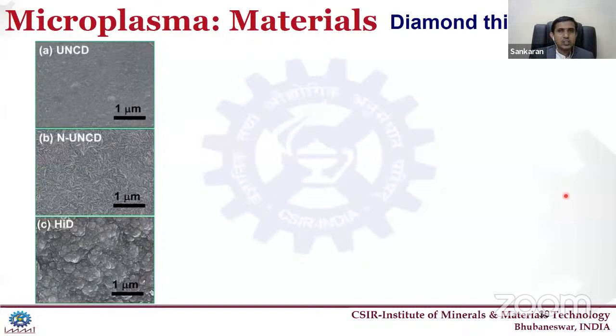By varying the input gases in the generation of the diamond thin films, we have developed various morphologies. The ultra nanocrystalline diamond films are called UNCD. The grains are nearly 5 nanometer in size. And next is the nitrogen doped UNCD, which has wire-like granular structures and is electrically conducting in nature. And this is called a hybrid diamond, a combination of UNCD and NUNCD.